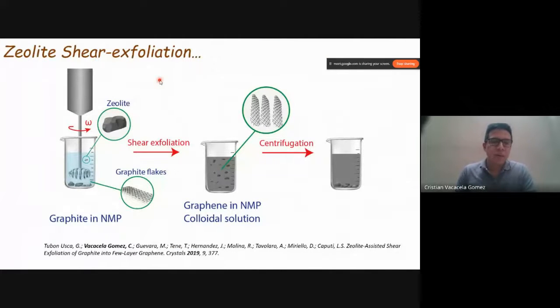And the last thing I want to comment about the synthesis methods for graphene dispersions is very simple. Maybe you can use just, for example, a glass with another organic solvent. We can put inside a mixer using zeolites. This is a macro system. By using just the concept of inelastic collisions, we can improve the sonication process, the exfoliation process in liquid media of graphite, to prepare graphene with high quality. There are a lot of methods, but now how does this method affect the graphene production, and of course, what are the material properties that we get after the application of this method? To answer these questions, we are going to use, of course, the Raman spectrum.